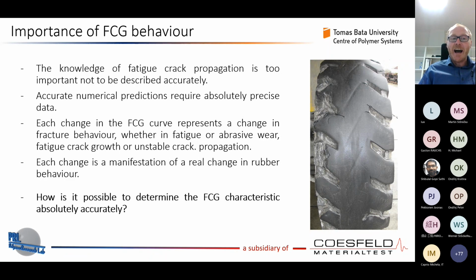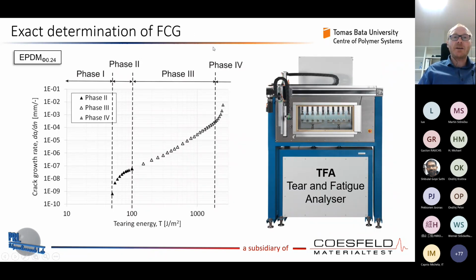And therefore, the main question is, how is it possible to determine the fatigue crack growth characteristic absolutely accurately and, let's say, completely from T0 up to TC, and once again, as accurately as possible. So, okay, how to do it? Exact determination of fatigue crack growth. We have here the example which Chris presented as well. This is an EPDM with filler fraction 0.24. What we did was perform a very detailed fatigue crack growth analysis with our tear and fatigue analyzer, so very detailed, to have as exact a curve as possible.